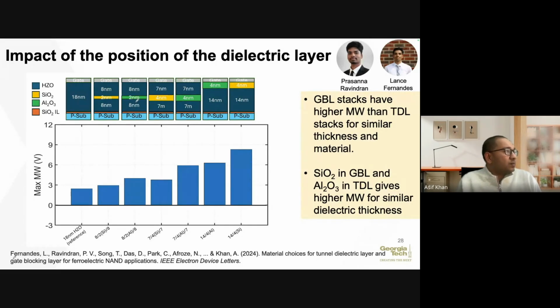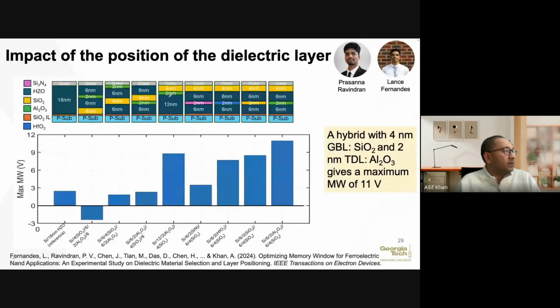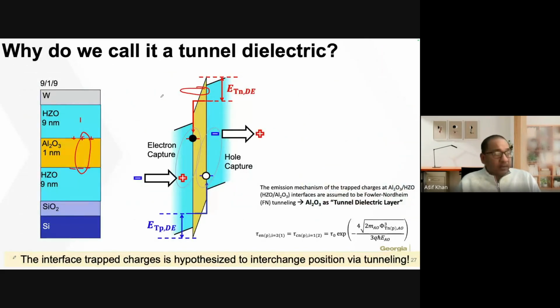So in the previous case, we showed that we had 8 nanometer HZO, and in the middle we had 3 nanometer of aluminum. So we went on and tried other choices of dielectric materials, and moved their positions around. And in this slide, I'm showing a bunch of different structures that we tried going forward. For example, here we had silicon dioxide, alumina, or silicon nitride, all these materials. And we systematically changed their position as well as their thickness.